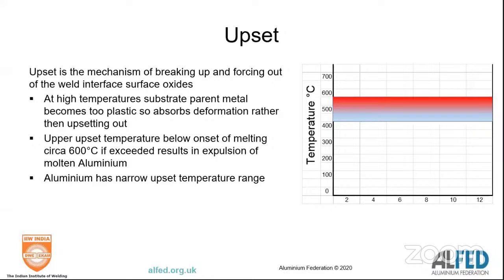A spot weld and mechanical and forge welds depend on upset. You use the heating to melt the aluminium, but then you have to upset it to get, in essence, the forge weld formed. Problem with aluminium is you've got very low strength. It goes very plastic very easily, very low melting points. So if you exceed them, you have problems. So the problem with aluminium is you need solid, strong aluminium to upset.